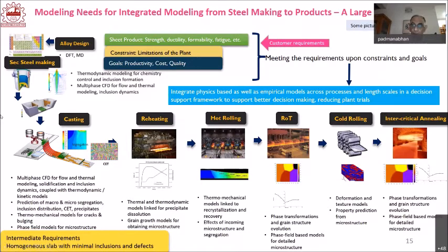But as I said, you start from quantum mechanics and go right up to macro scale. That is vertical integration. For example, just take casting. Here, you require multi-phase CFD flow and thermal modeling, solidification and inclusion dynamics, coupled with thermodynamic and kinetic models, prediction of macro and micro segregation, inclusion distribution, columnar to equiax transition, precipitates, and then thermomechanical processing models for the presence of cracks and bulging. Bulging comes out because of the release of dissolved gases as the temperature goes down, and that leads to a certain degree of bulging. And of course, it can also happen if there is wear and tear in your continuous casting equipment. Some bulging will come because of the larger gap that is developed because of the wear of the equipment. So that also is possible.